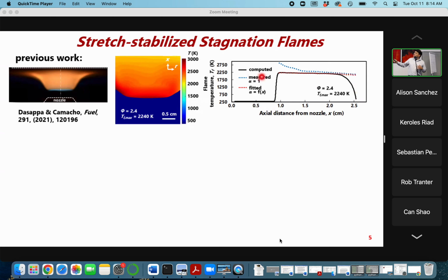And by fitting this optical dispersion coefficient to our computation, it shows that within physical reasonability our temperature makes sense. It's not a perfect independent temperature measurement, but my point here is that we indeed have hotter flames than normal, much greater than 2000 Kelvin.